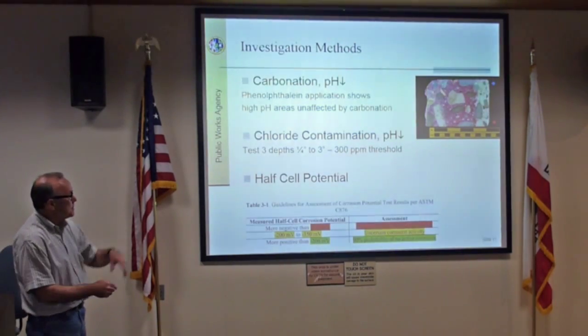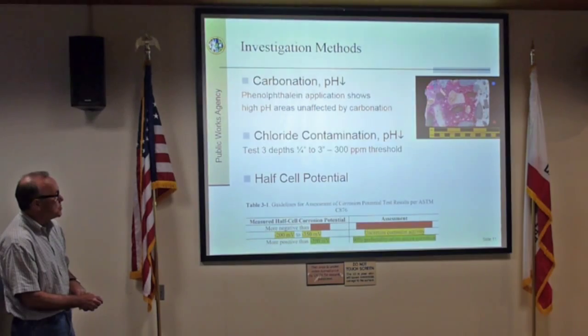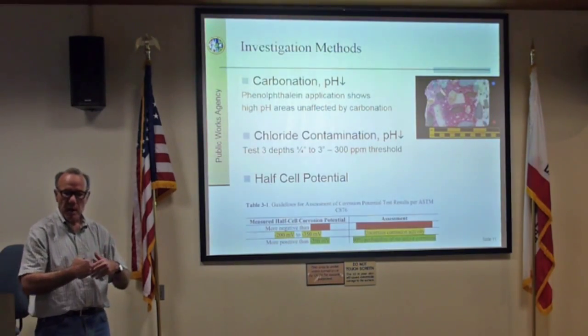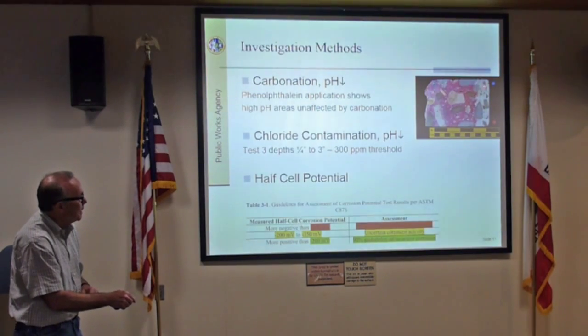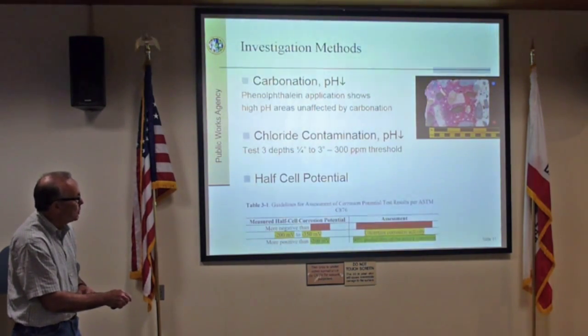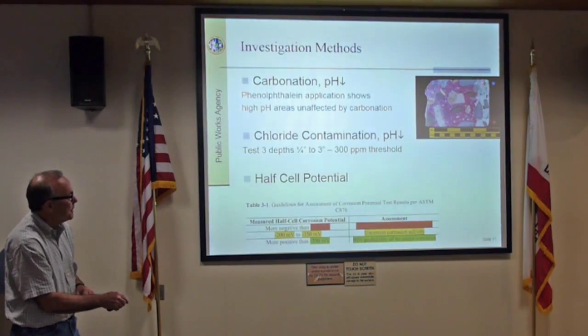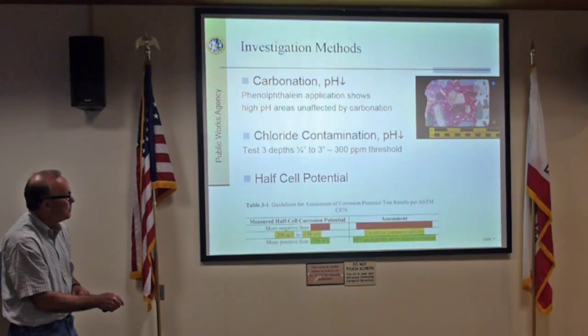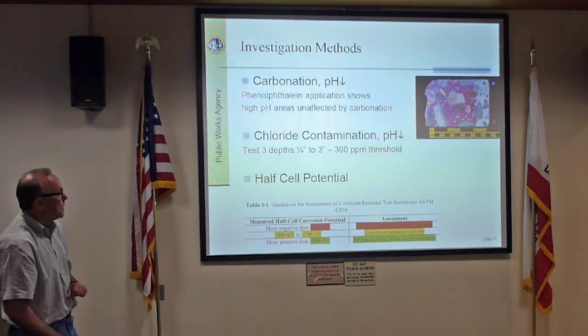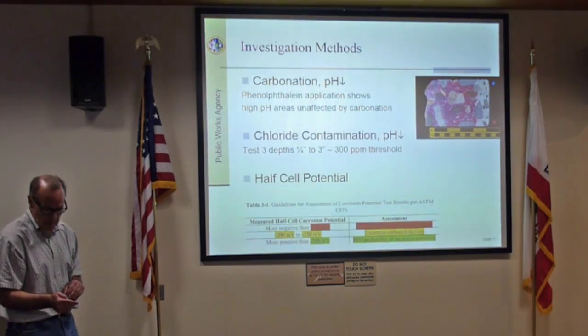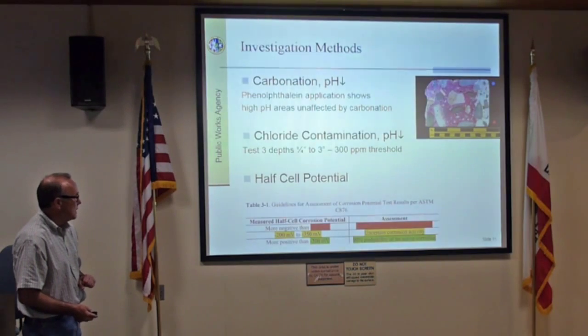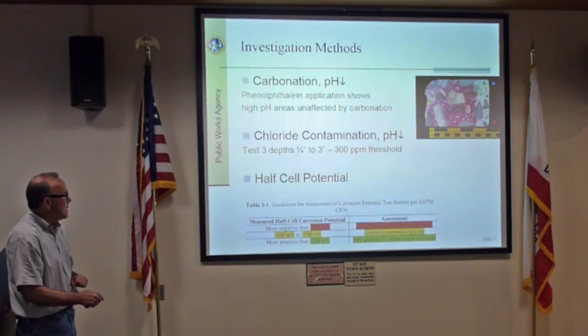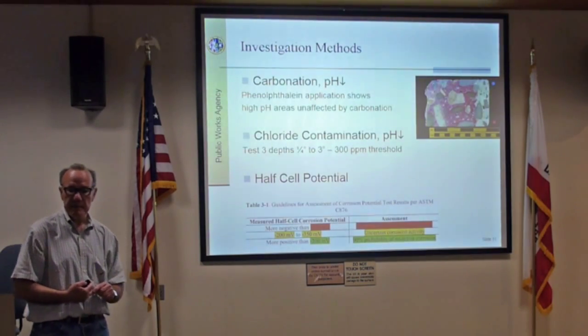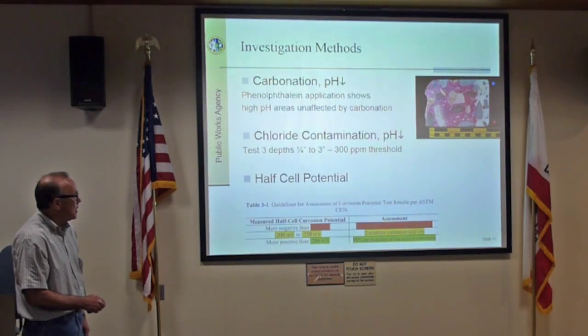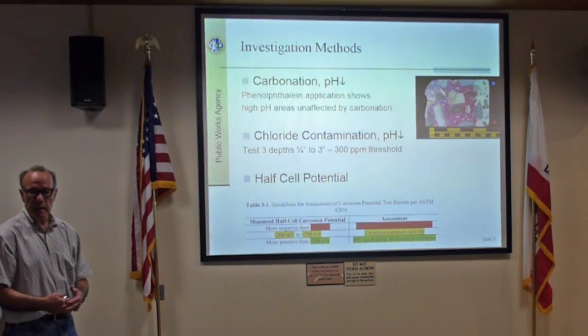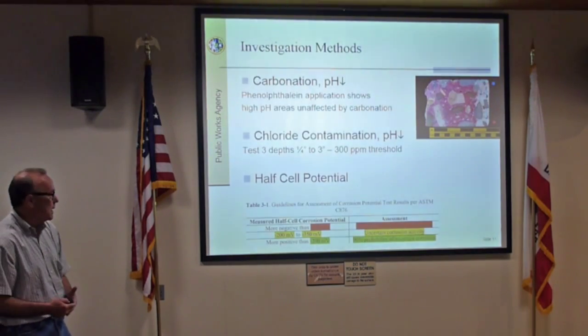Carbonation is a chemical test; wherever it's red is high pH. We don't have to worry about it. There's a natural process where this layer at the top, where the pH gets lower, can be vulnerable to corrosion. In highly industrial areas of the United States, this carbonation front can move down. When it's at the level of reinforcement, say down here, you can get corrosion due to carbonation. That's not much of an occurrence that we see here in the Ventura County walls. Chloride contamination: chloride, in essence, accelerates the corrosion whenever we get more than about 300 parts per million, which is the threshold where we're concerned about chloride-induced corrosion. We had some cases of that.